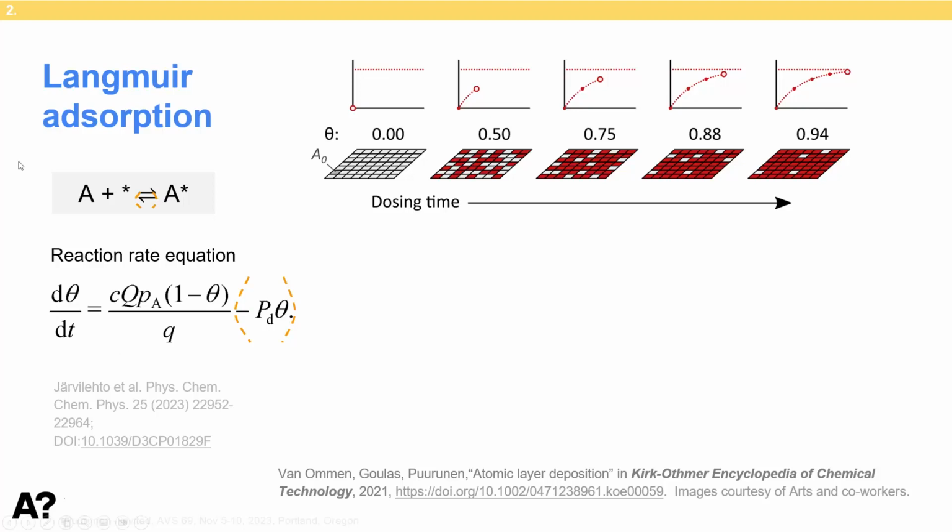So there's the sticking coefficient, there's a term related to partial pressure and the impingement rate on the surface. There is the fraction of unoccupied surface sites, and then there is the adsorption density, or 1 over this would be the size of an adsorption site. And if you allow reversible reactions, then there's this forward reaction rate and the backward reaction rate.